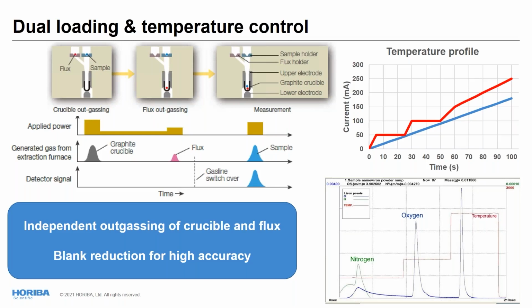And then we have a specific setup to introduce the flux that may be needed to help the sample to melt. We are using what we call the dual loading system, to drop independently the flux and the sample into the crucible. That means the system will be able to outgas the crucible. Then we will be able to introduce the flux to outgas the flux, and then to introduce the sample to perform the analysis. This will result in a blank reduction and improve the accuracy of the measurement.